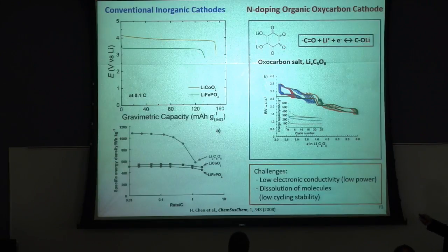Then if we see this small molecule, introduced by Professor Tarascon's group in 2008, this small molecule has 4 carbonyl groups. Each carbonyl group can react with a lithium ion and store 1 electron. So this is the charging discharging profile of this oxocarbon salt. We can clearly see this molecule can store 4 lithium per molecule. If we calculate the capacity, it is pretty high, more than 400 milliampere hours per gram.